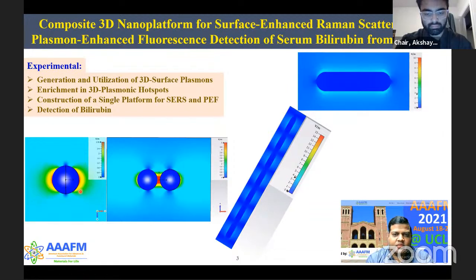And the surface plasmon resonance is largely geometry dependent. For example, in the case of nanorods, a very little change in the aspect ratio of the nanorods leads to a shift in the plasmon resonance. So we are particularly interested in silver nanowires.